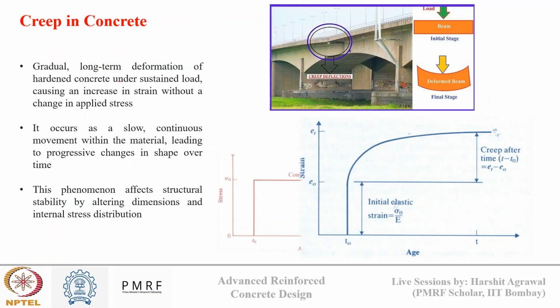Okay, so in this sustained loading, what will happen? There will be an increase in strain without change in the applied stress, and this increase in strain is known as creep. This creep occurs due to slow continuous movement within the material, which leads to progressive change in the shape over time. You can see one example of this creep in this image here, where you can see a bridge deck under continuous loading.